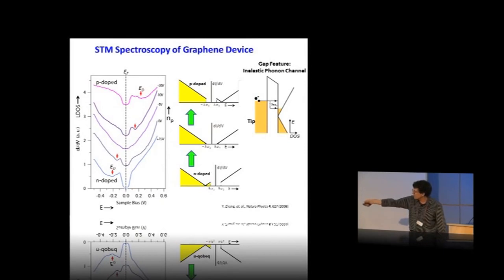This is a plot of dI/dV versus bias voltage between the tip and the surface. This is the Fermi level, and here we have filled states and empty states, and each of these curves is measured at a different gate voltage. We're becoming more and more p-doped as we go up each additional curve, so the density of states is shifting to the right as you go up those curves due to the gating. Here we saw two features. One was this gap-like feature that's pinned to the Fermi level, and the other is this asymmetric dip off to one side.